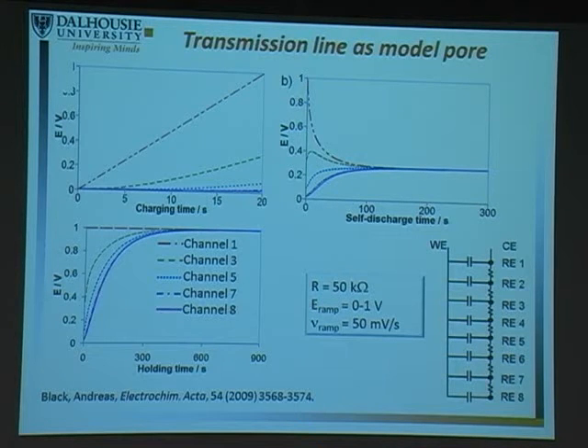Again, exactly what we would expect in a pore, and that potential drops. And the potential of the capacitor deep in the circuit, or the potential at the bottom of the pore, climbs until they reach an equilibrium. So our model is working appropriately. We also tested to make sure, of course, that if we held the potential at a certain value, so we've charged it up, and then we hold the potential, that all the capacitors would reach that final potential, and of course they do. So nothing surprising here.